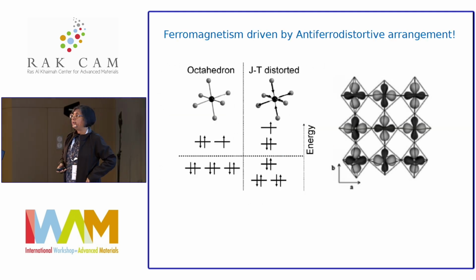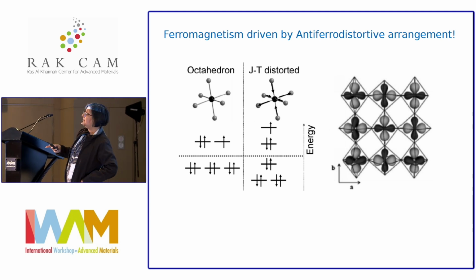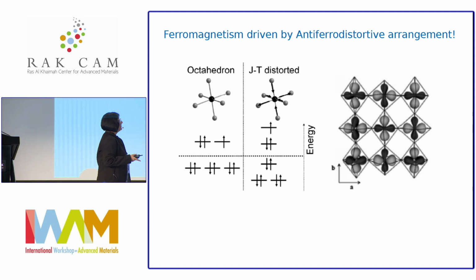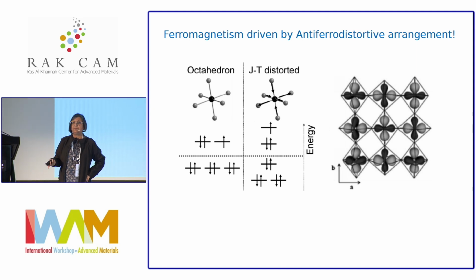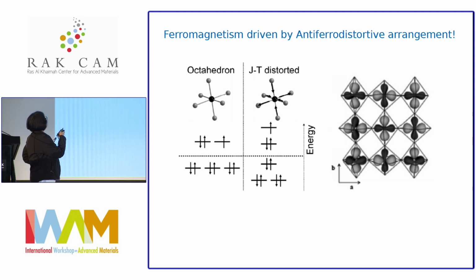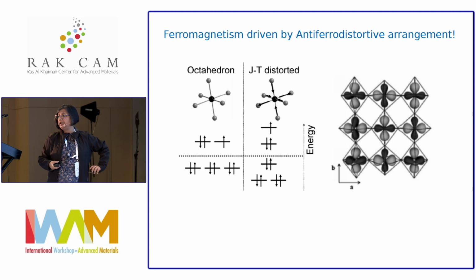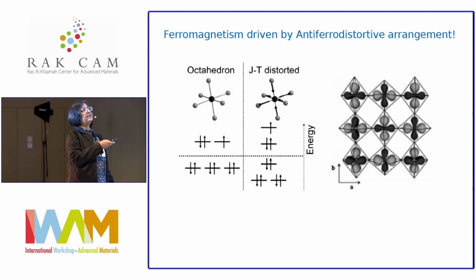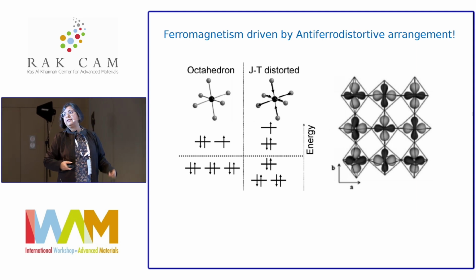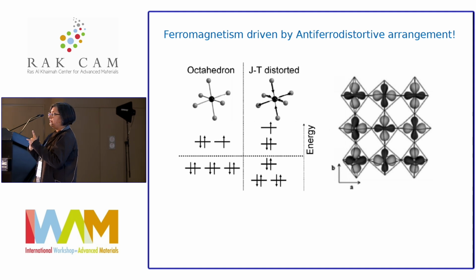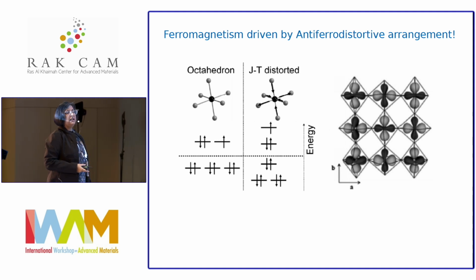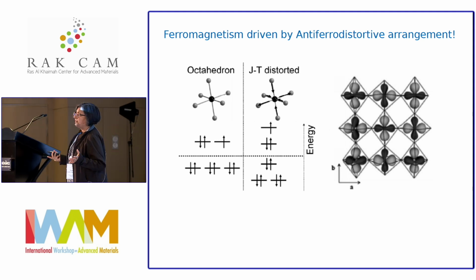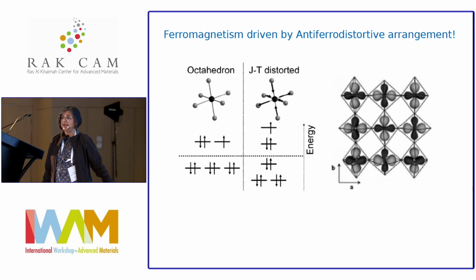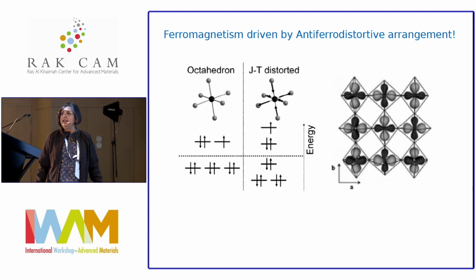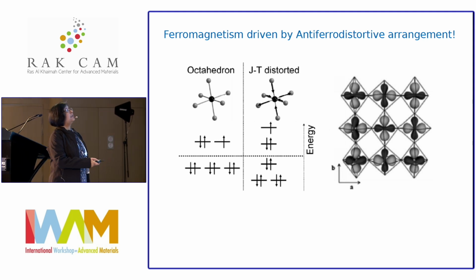Now, what causes this ferromagnetism? As I said, the valence configuration is important. They have copper 2+, which is Jahn-Teller active. They have chromium 2+, d4, which is also Jahn-Teller active. And because of this Jahn-Teller activity, you get four short bonds and two long bonds. And there is what is known as an antiferrodistortive pattern. That means the long bond of one octahedron faces the short bond of the neighboring octahedron. As a result, it promotes ferromagnetism because orbitals of two different symmetries point towards each other. So that's the key to the ferromagnetism seen in these materials.